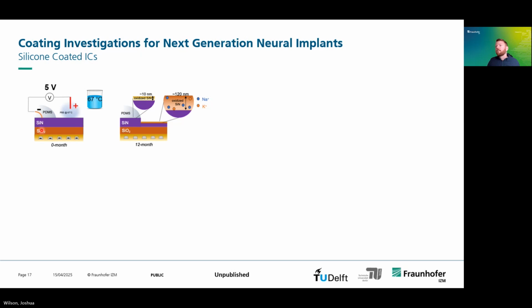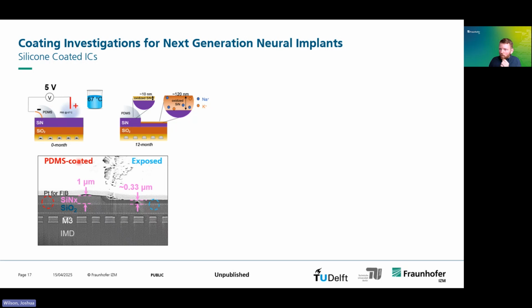So here we took the device. This is the silicon nitride surface, and this is a silicone, and so it's only partially coated. On the left hand side is coated, on the right hand side is not coated. Now what you see here in a cross section of this device is that in the area that is coated, there is not very clearly any degradation, and in the area that's uncoated, exposed to the saline solution or the body fluid, you see some degradation.